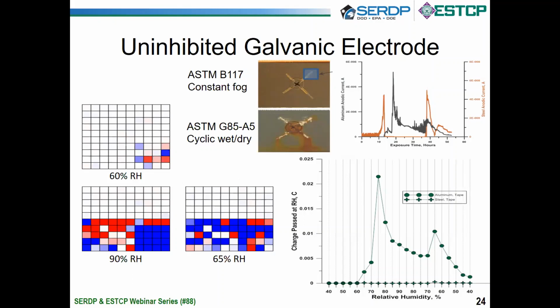So why this is important is because if you're cycling tests, if you have very short wet cycles in those tests, and very short dry cycles, these surfaces may not come to some kind of steady state condition as they're passing through wetting and drying, and you end up with very high corrosion rates. And as I mentioned on the last slide, what you see as sub-deliquescence corrosion can be significantly different than what you see in corrosion that occurs above the deliquescence point.